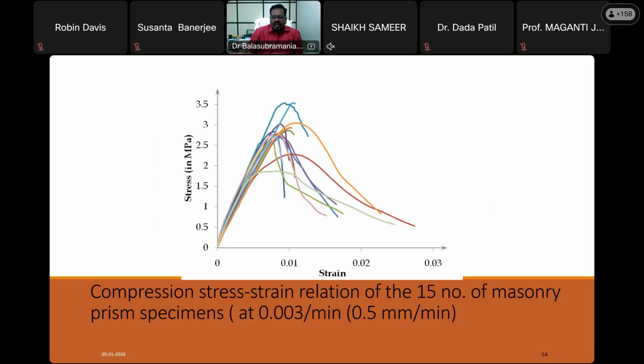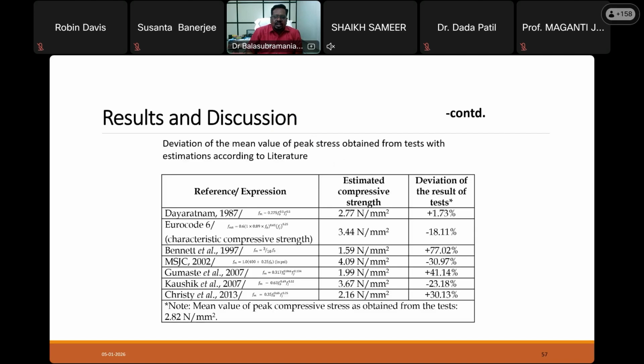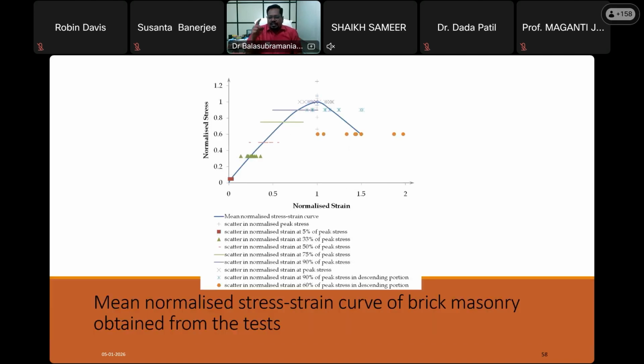This is the absolute scale, and then we normalized that. With respect to the peak load and the strain corresponding to the peak load, the same scattered curves, we normalized them in this fashion. Now one can easily understand how to characterize, right? By normalizing with respect to the peak load and the strain corresponding to the peak, we can get the normalized curve and typically characterize this stress strain relation.